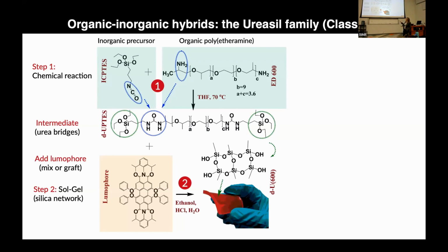And we react this then with any type of off-the-shelf polymer, typically these polyether amines that have functional reactive amine groups. In this case, we've got two. So we can bridge at two sites. And so the isocyanate and the amine react together. We form these urea bridges. So you can see where the urea part of the name comes in. And at this point, we have our intermediate. And at this point, we can add our light emitting species, our lumophore. And we can do that in a number of ways. And we'll look at that in a second.